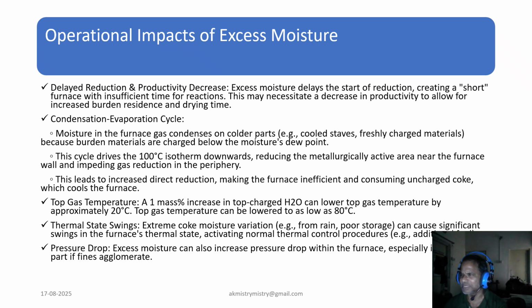Excess moisture delays the start of reduction, essentially creating a short furnace with insufficient time for reactions. This often necessitates a decrease in productivity to allow for increased burden resistance, with the effect on residence time and, at the same time, drying time also. Secondly, we face a condensation evaporation cycle.